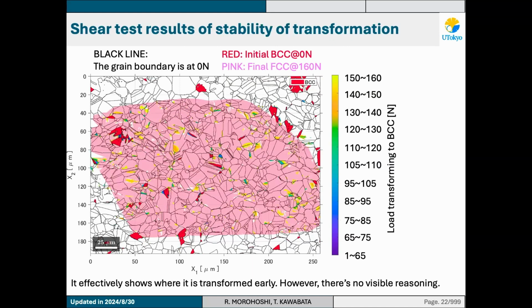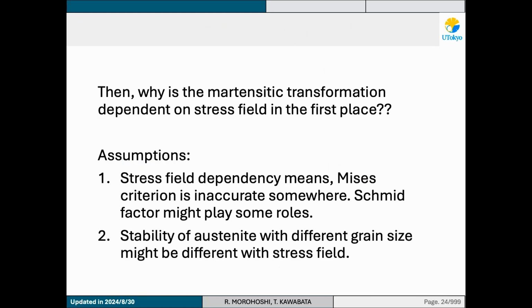And this is a shear one. And obviously the austenite is much more stable. This is the uniaxial one. And in the first place, the martensitic transformation was dependent on the stress field. So I made two assumptions. The first is that the stress field dependency means this criterion is inaccurate somewhere, so maybe the Schmid factor plays some role. And the second is that the stability of the austenite with different grain sizes might be different with the stress field.